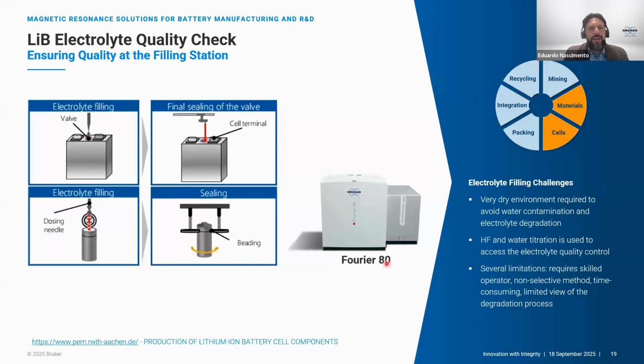So here we know that the challenge when we talk about electrolyte, at least in my mind, the very first thing that comes to mind is the dry environment. That's because the electrolytes that we normally use in the lithium-ion battery, due to the presence of conducting salt like lithium PF6, they don't like water at all. So as soon as electrolyte is in contact with the minimal amount of water, it will start to degrade.